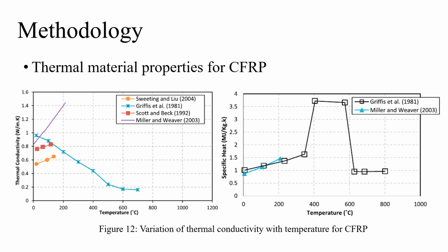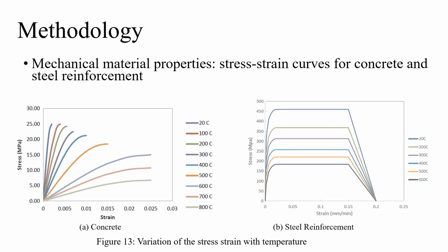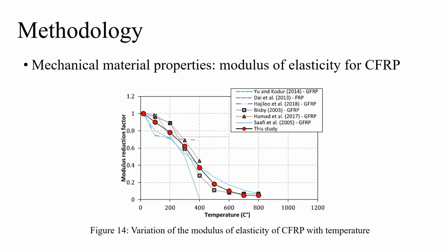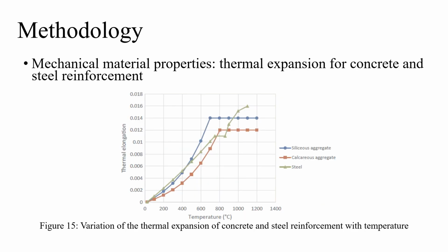Previously proposed models were adopted for the variation of the CFRP material properties with temperature. In this study, the Griffis et al. model was used. The mechanical material properties include modulus of elasticity, thermal expansion, and stress-strain curves. For concrete and steel, they were also calculated using Eurocode 2. Since CFRP is a linear elastic material, only a modulus of elasticity model was assigned. It was adopted from a previously proposed model in the literature. And this is the variation of the thermal expansion with temperature for concrete and steel, calculated from Eurocode 2.